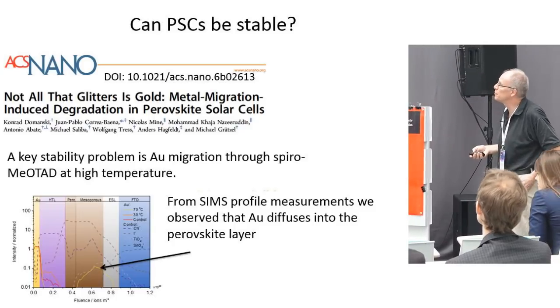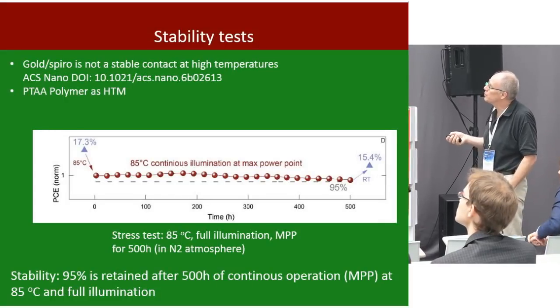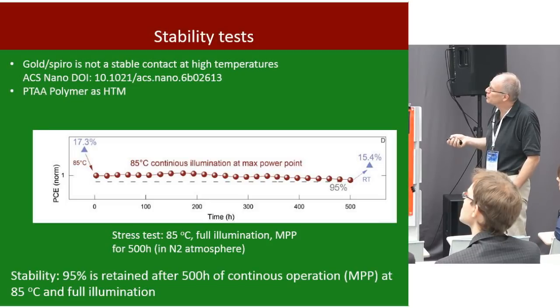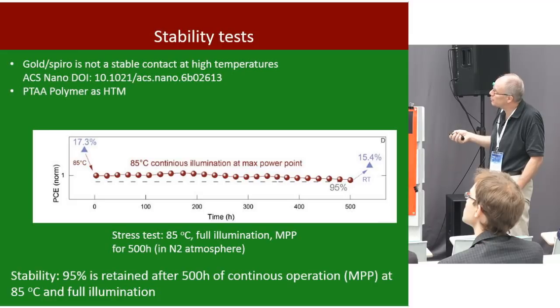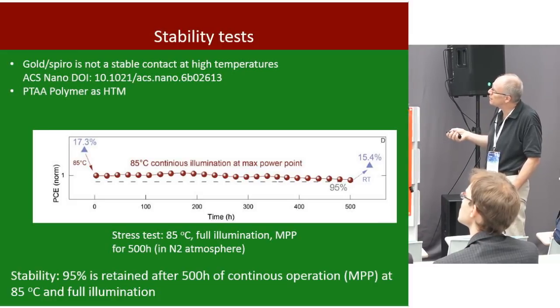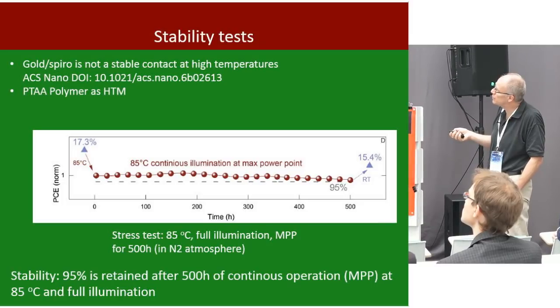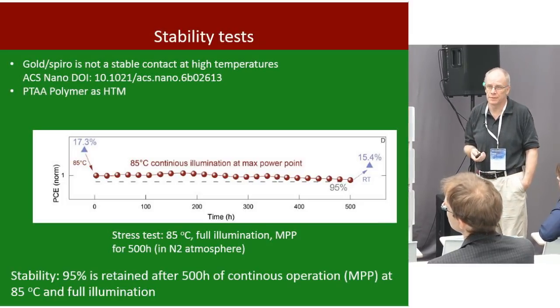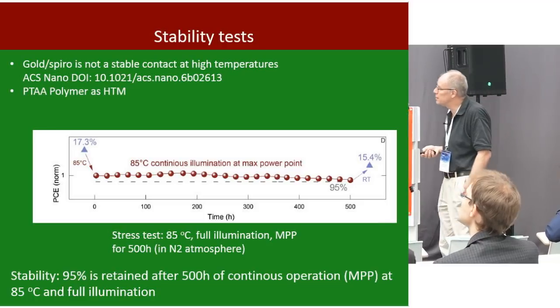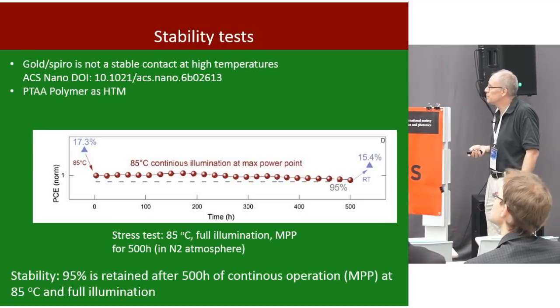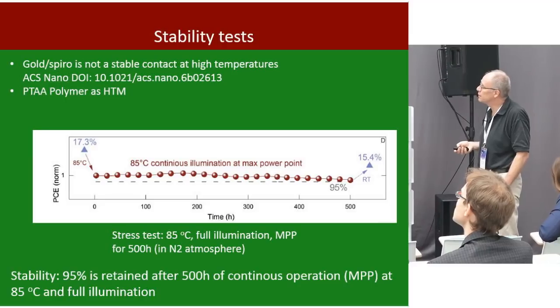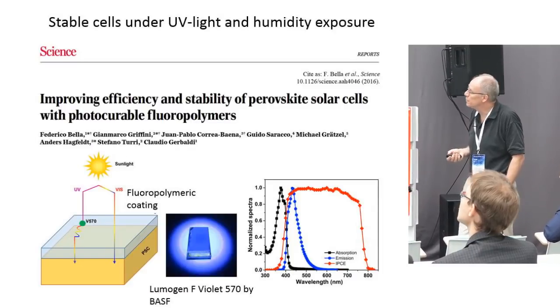So that we have to avoid gold on spiro, I should say. So solving that problem, to replace spiro with a polymer, we could get this stability at 85 degrees. We start here, take it to 85 degrees, illuminate it for 500 hours. It's running and operating as a solar cell all the time, and we are almost keeping the same efficiency as we started at 85 degrees. So that's very promising, let's say. So I think there is reason to of course be worried about stability, but for sure there are possibilities too.